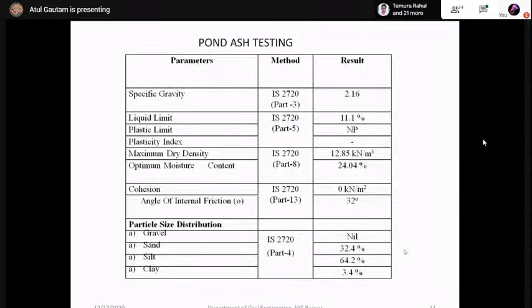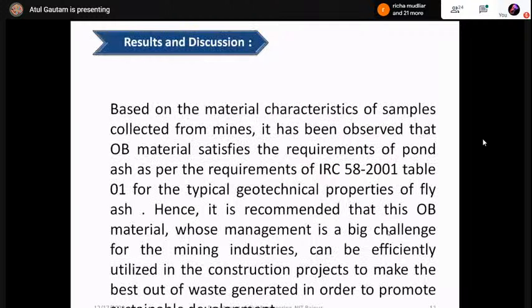So we have also conducted a test on the pond ash. This pond ash sample is collected from NTPC Mauda, which is approximately 40 kilometers from Nagpur, and we have determined all these geotechnical properties of the material collected from this site. Then result, based on the material characteristics of sample collected from mines, it has been observed that OB material satisfied the requirement of pond ash as per the requirement of IRC 58/2001 table number 1. Basically, this OB material is just similar, it satisfies all the requirement of this pond ash, and hence it is recommended that this OB material, whose management is a big challenge for the mining industry, can be effectively utilized.